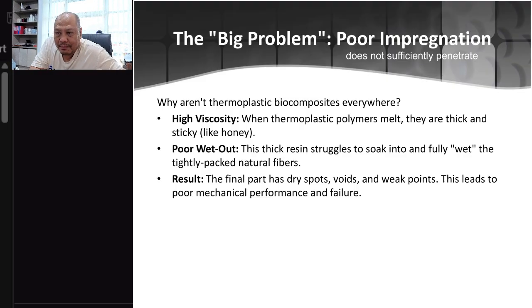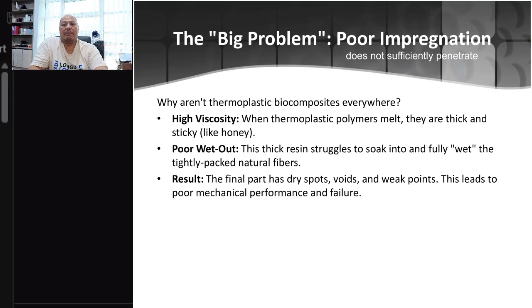And then the big problem of this product is poor impregnation, which does not penetrate sufficiently. Why aren't thermoplastic biocomposites everywhere? Because they have high viscosity. When thermoplastic polymer melts, it is thick and sticky like honey. This thick resin struggles to soak into and fully wet the tightly packed natural fiber. As a result, the final part has dry spots, voids, and weak points. This leads to poor mechanical performance and failure.